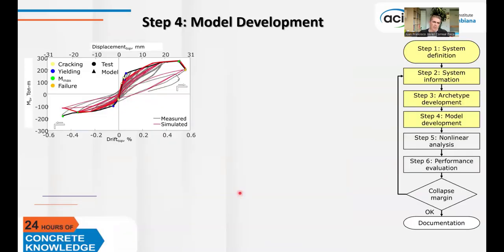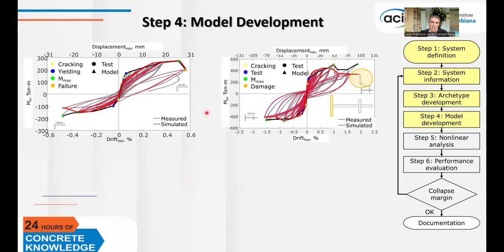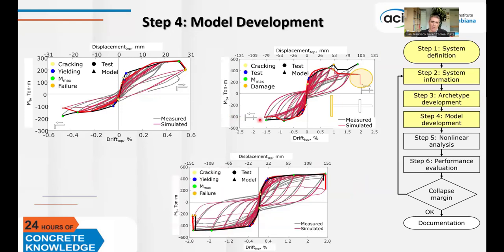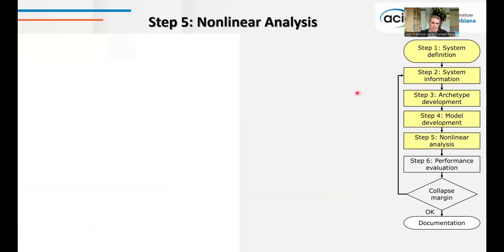And here are the experimental results compared with the computer simulation. As you see, there is very good agreement, not only for L-shaped walls, but also for I-shaped walls, as well as for rectangular walls with boundary elements. Something very important for the model is that you need to be able to predict the failure of the walls. This is something that the FEMA methodology asks for.